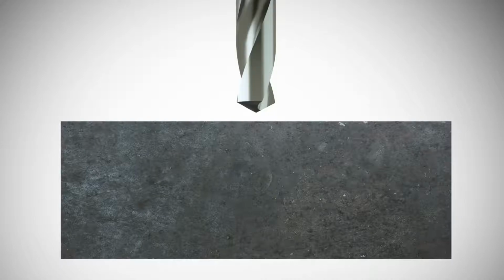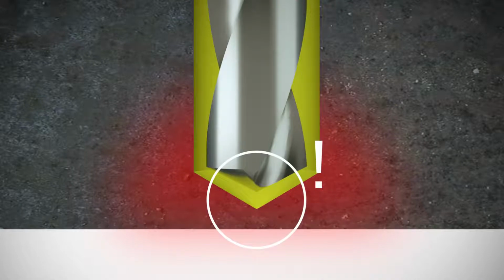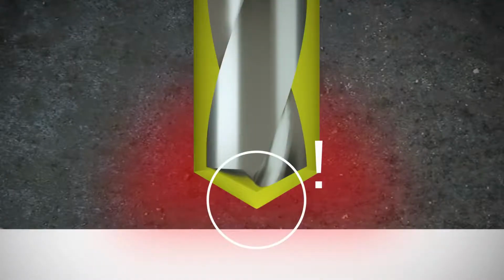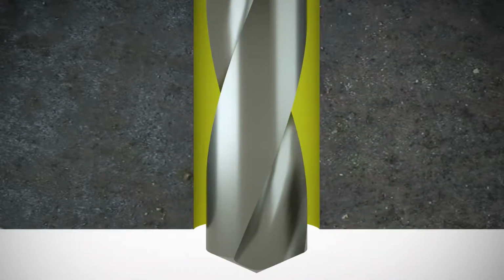When drilling holes that break through the workpiece, pay special attention to the material and cutting conditions. Drill manufacturers recommend slowing the feed rate before the drill point breaks through the material to prevent chipping and reduce heat in the cut. We want to reduce the heat because as the drill gets to the very bottom, before it breaks through, the material is very thin and there is no place for the heat to go. So that last bit of material can work harden, literally heat treating the material. Breaking through this heat treated layer can shorten the life of the drill. A 50% reduction in feed rate for the final 2 millimeters or 100 thou before the drill point reaches the bottom usually eliminates this issue.